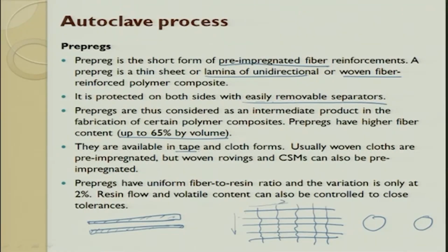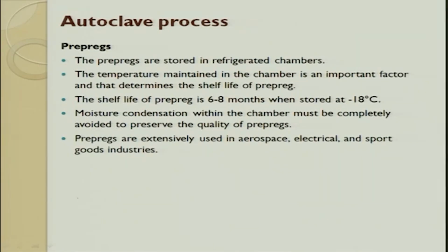They are available in tapes and in cloth forms. Usually woven cloths are pre-impregnated, but the woven rovings and CSM are not. They can also be pre-impregnated, but generally we do not do it. Here the fiber to resin ratio is uniform, and the variation will be as low as 2%. That means you will get a very, very sound product.